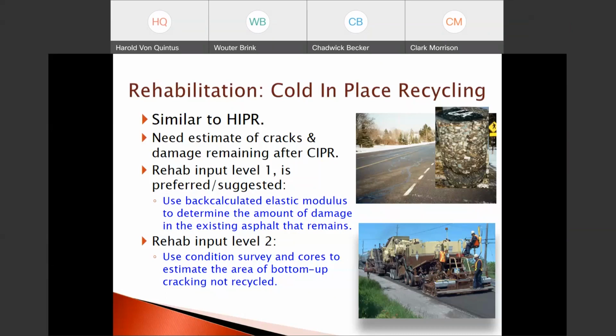Rehab input level 2, we used a condition survey and cores to estimate the area of bottom-up cracking that's not recycled. Again, the same thing would be suggested where if we're just doing rehab input level 2, any cracking that's seen on the surface and the wheel path, we assume that's bottom-up cracking. And so that would go through the entire asphalt layer. And so that's the amount of fatigue cracking in the existing surface, bottom-up cracking, we would include in pavement ME. If we have cores and we know most of the cracking is top-down cracking at the surface, then that would not be the case.